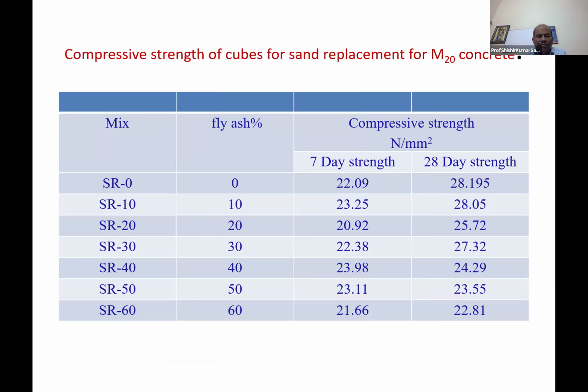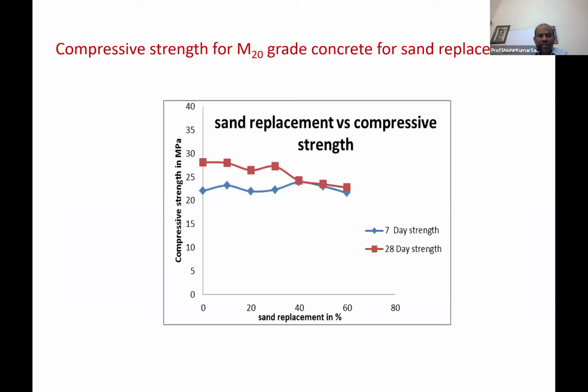As you can see, the compressive strength initially increased with 10%, but gradually decreases, and sometimes you can see SR20 decreases, but SR30 increases. So that kind of thing is seen in slag cement, but OPC shows clear trends. This is the sand replacement versus compressive strength. The 28-day strength up to 60% of replacement.